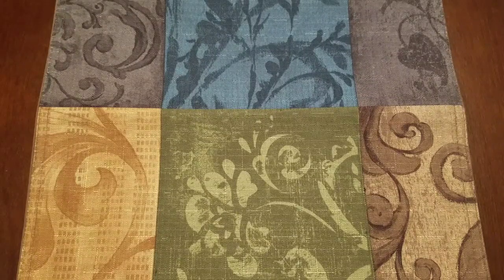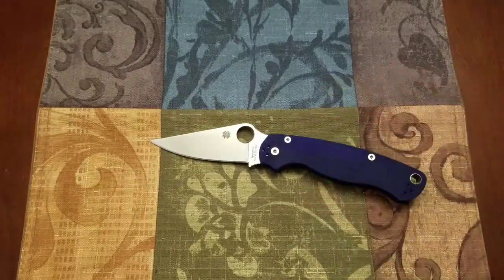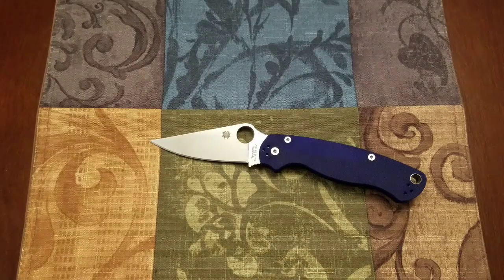Now, another high-end stainless steel is made by Crucible Steel in America, and that is CPM S110V. It's also a powder metallurgy steel. It has a very high wear resistance and good corrosion resistance. Now, it has the addition of niobium, an alloying agent in these steels, and there's so many of them, I'm not going to go over all of them. But niobium is what you call a carbide former. It forms carbides, small particles within the matrix of the steel that are harder than anything around it.